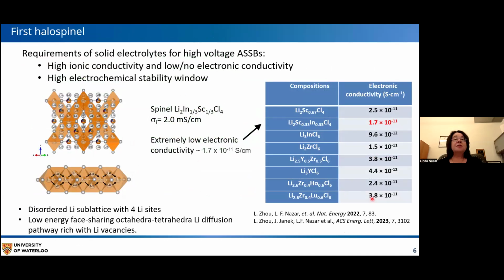So on the subject of this spinel, and actually materials in general, not just the spinel, the requirement of a solid electrolyte is not just high ionic conductivity, but also very low electronic conductivity. And this is one of the things that gives rise to a high electrochemical stability window. And so my graduate student, Lidong Zhou, who's now a professor in China at Nanjing University, carried out some very careful electronic conductivity measurements on a host of these different materials. And you can see that they all have very low electronic conductivity in the vicinity of 1 or 2 times 10 to the minus 11 Siemens per centimeter.